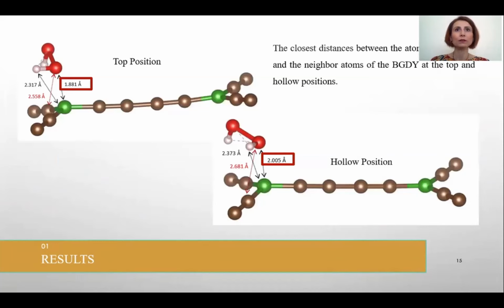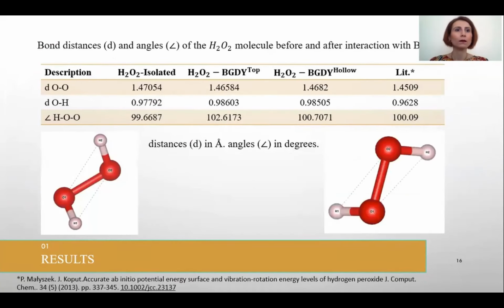For both positions, hollow and top, the closest distance between the oxygen and boron is shorter for the top position, which means hydrogen peroxide bonds more strongly than at the hollow position. For the optimized molecular structure of hydrogen peroxide, the bond lengths and bond angles are listed for the isolated molecule and after interaction with boron graphdiyne.